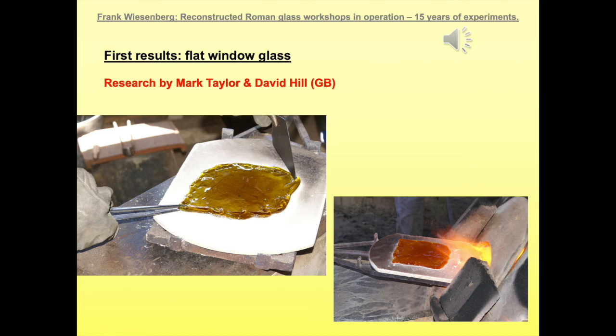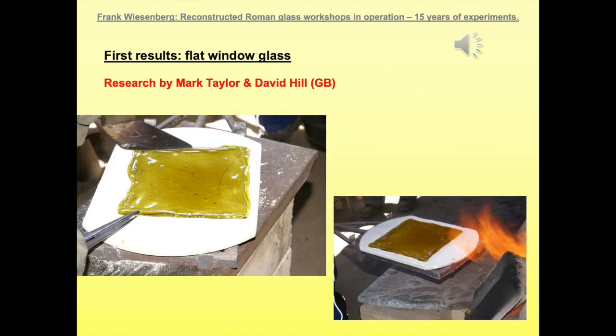This is transferred to a ceramic support, which again, such as the mosaic glass and rib bowls, can be used for reheating the glass blank inside of the glass furnace. This is a process which has to be repeated a couple of times. After frequent procedures of reheating, pulling, stretching, flattening, and pushing backwards, we end up with square glass plates, which